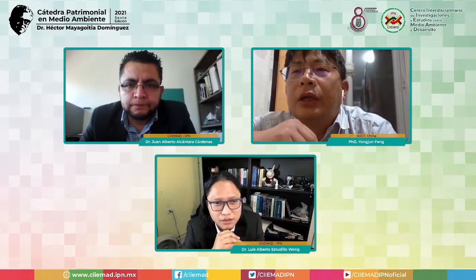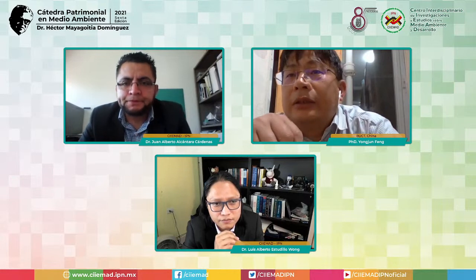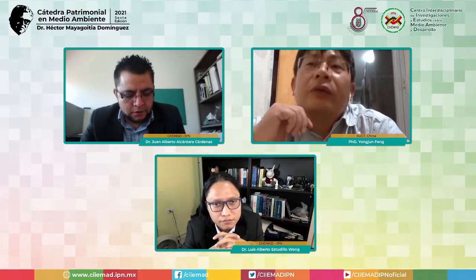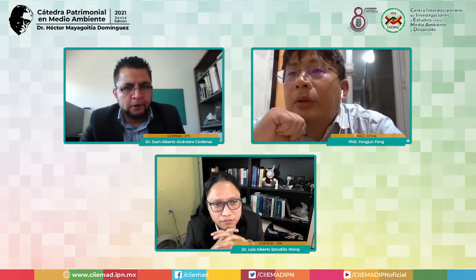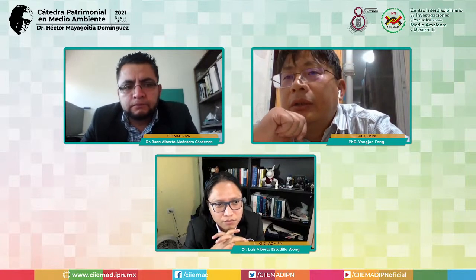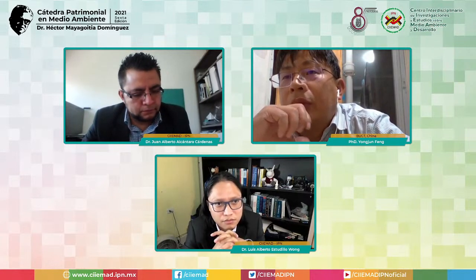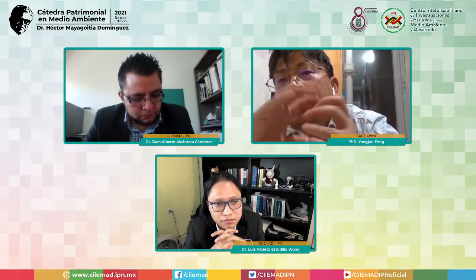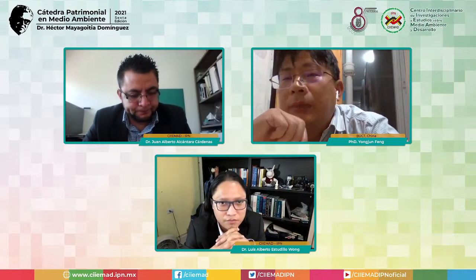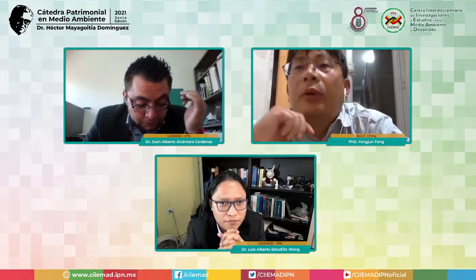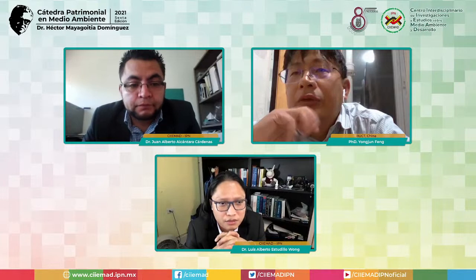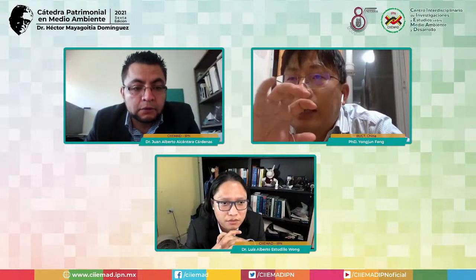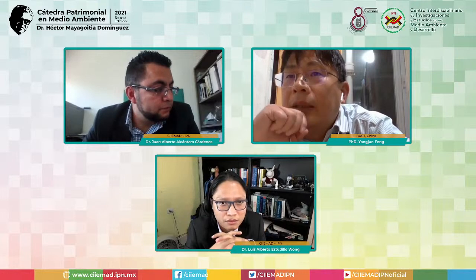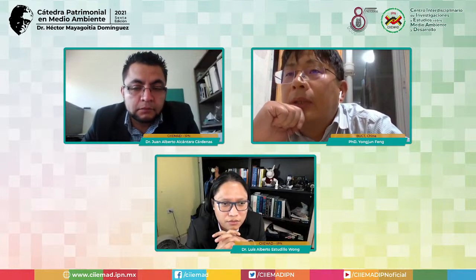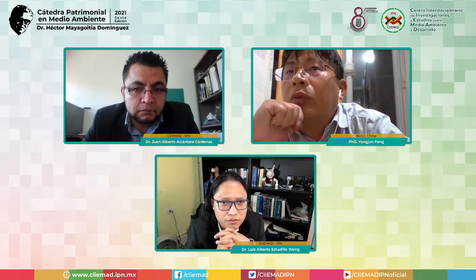Because the LDH is a metal hydroxide, the conductivity is not very high. So we need the carbon support or RGO to increase the conductivity. That's why we disperse the LDH in RGO. That means we can control the dispersion, so we can work on both sides. We combine the LDH with carbon oxide, active carbon, or RGO and other carbon. We can increase the conductivity.